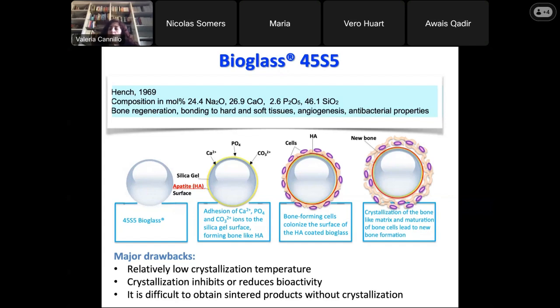45S5 bioglass was the first bioactive glass produced by Professor Hench, and it is able to bond both hard and soft tissues. Moreover, 45S5 stimulates angiogenesis, vascularization, and it has an antibacterial activity. However, bioactive glasses have shown some drawbacks, in particular their tendency to crystallize during thermal treatments. But such thermal treatments are necessary in several processing routes, such as the production of sinter materials, coatings, and scaffolds for bone tissue engineering. Besides slowing down or inhibiting the sintering process, the partial crystallization of a glass may reduce the biological performance of a final product and lead to implant instability once placed in the body, because the residual glassy phase is degraded preferentially.